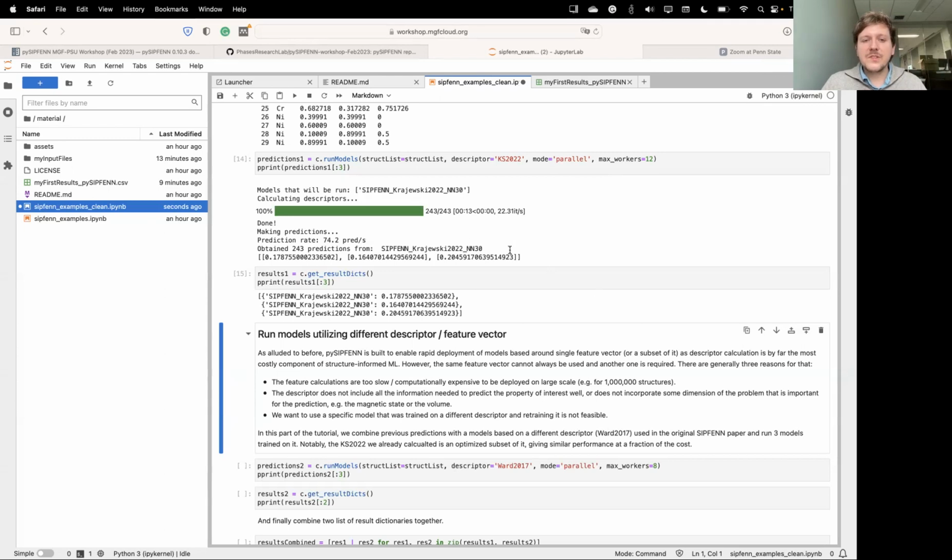So if you scale the cell in all 3 dimensions equally, then the thing that you're scaling is only the volume. And PySIPFENN, as explained, is volume independent, unlike some other methods, but at the same time, it doesn't require volume relaxed input. If you scale one of the dimensions, like for example, you take a cubic cell and make it tetragonal, then the energy is going to change quite significantly. If it's for example, a BCC iron cell, it's gonna depend in this fashion.